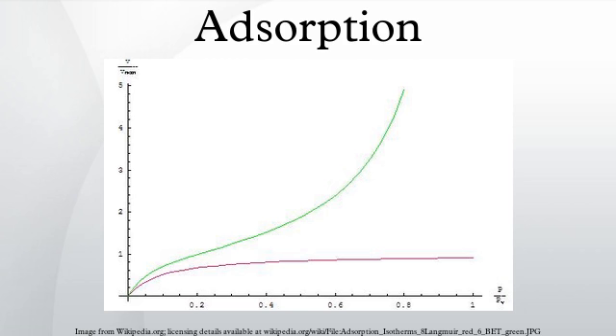Portal site-mediated adsorption. Portal site-mediated adsorption is a model for site-selective activated gas adsorption in metallic catalytic systems that contain a variety of different adsorption sites. In such systems, low coordination edge and corner defect-like sites can exhibit significantly lower adsorption enthalpies than high coordination sites. As a result, these sites can serve as portals for very rapid adsorption to the rest of the surface.